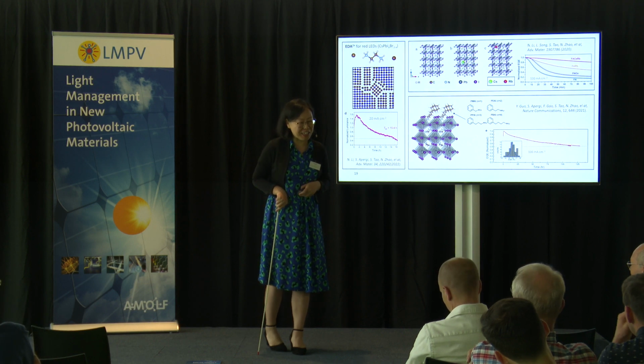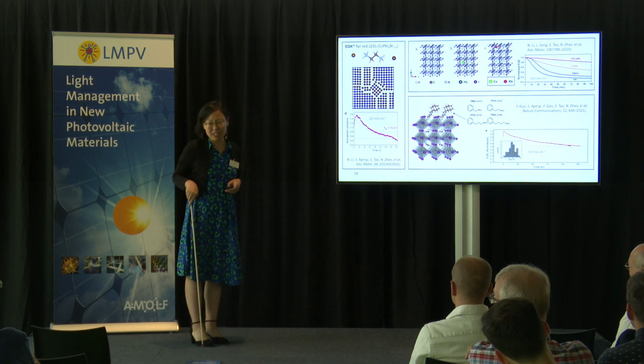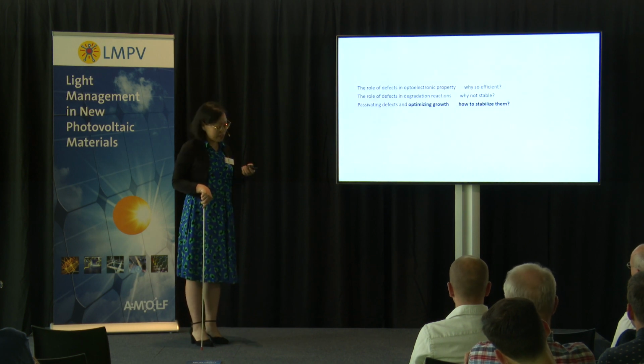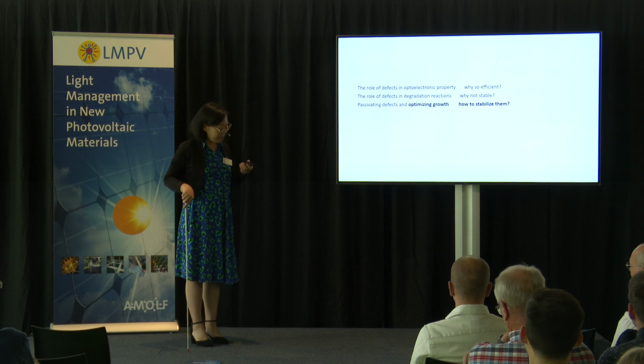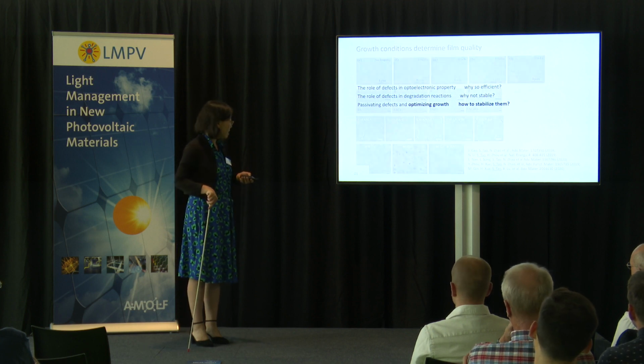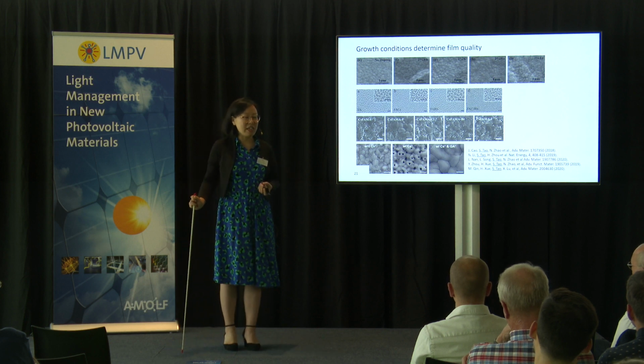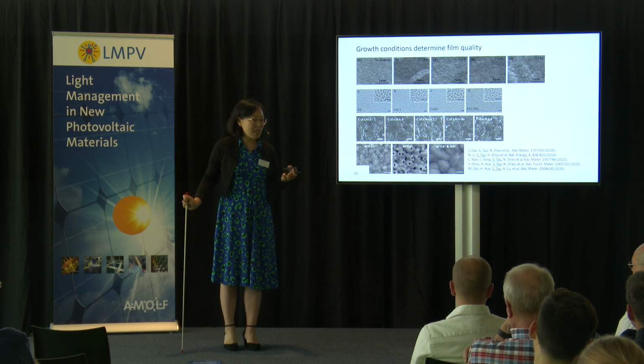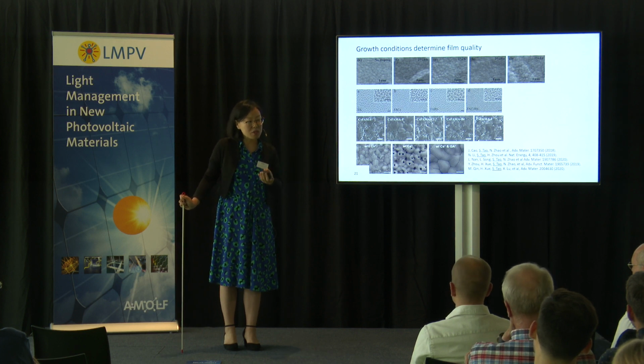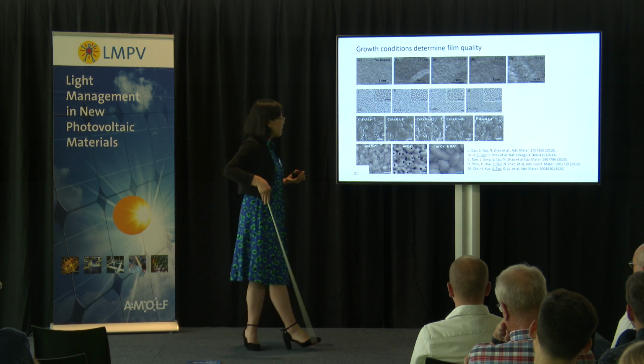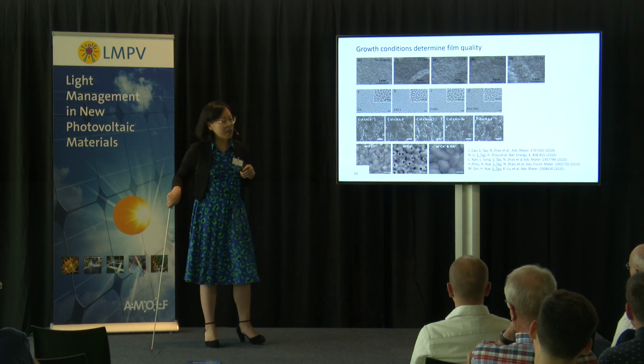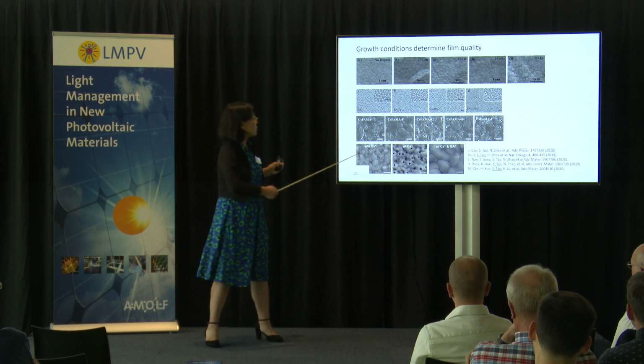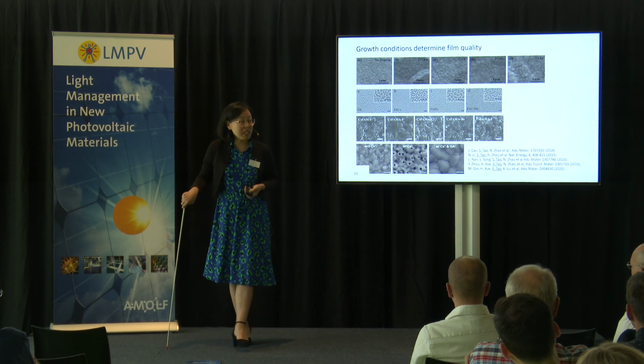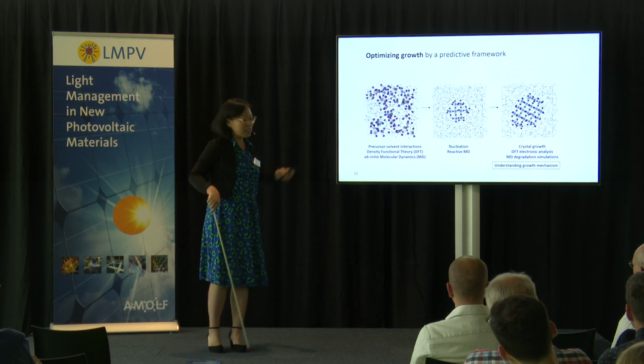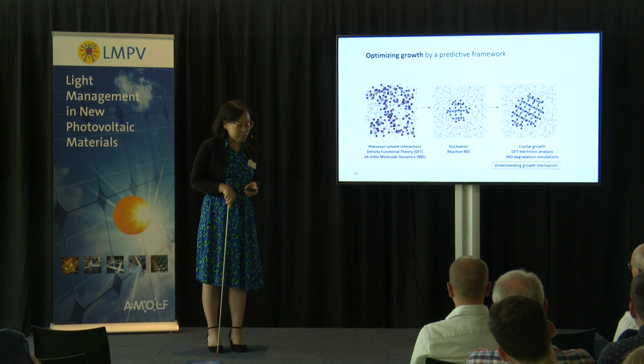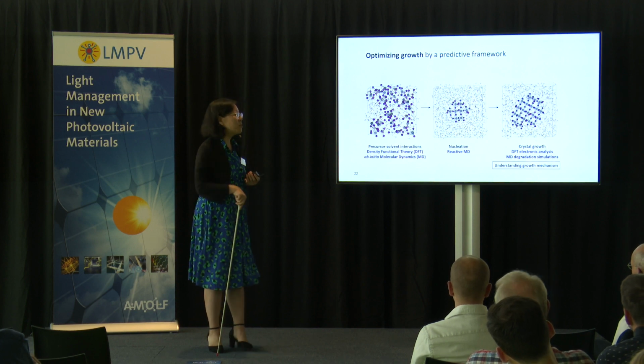Okay, I think I have shown you enough examples about stability and how to passivate the films. But so far, we're only looking at the passivation effect. We forgot one effect: when we make the film, all the things we already added in the beginning, all the chemical interactions we were just mentioning, also impact how the film grows. And you can see this is exactly some of the examples I showed above. By adding a little bit of different chemicals, you grow totally different films. This means fundamentally, to stabilize this type of material, it lies in how to grow perfect crystals without defects, how to optimize the growth.